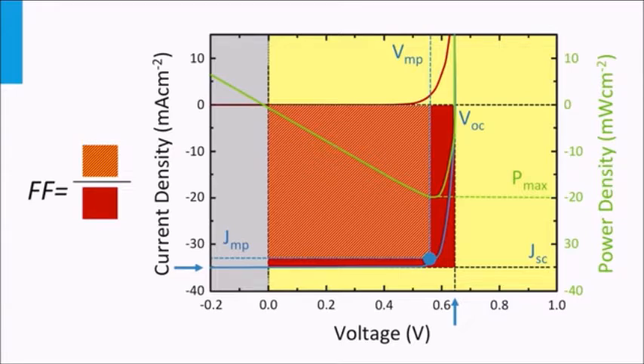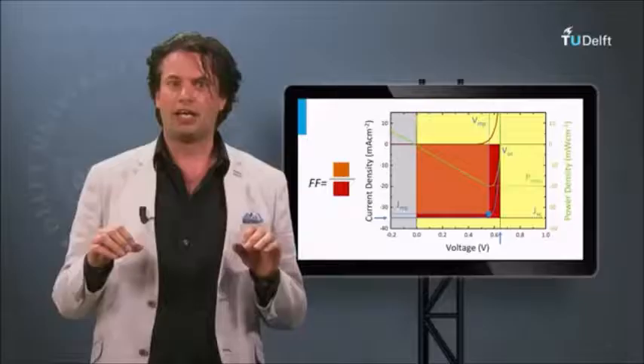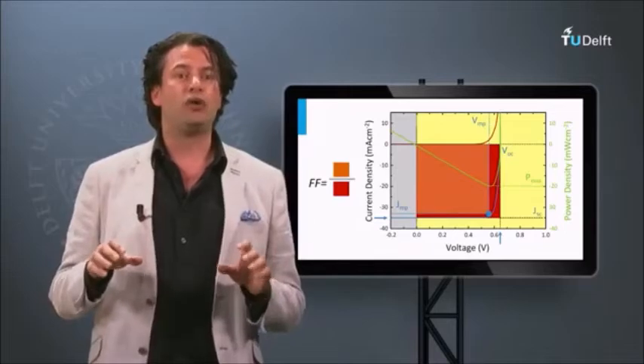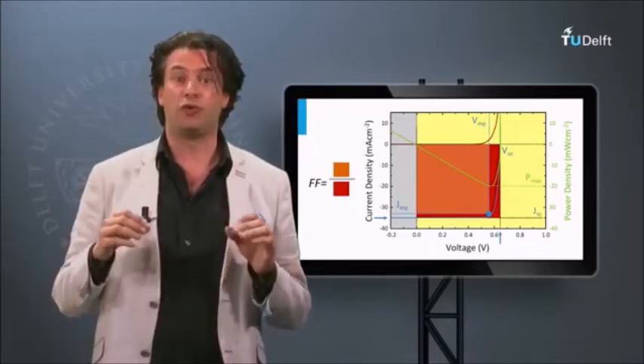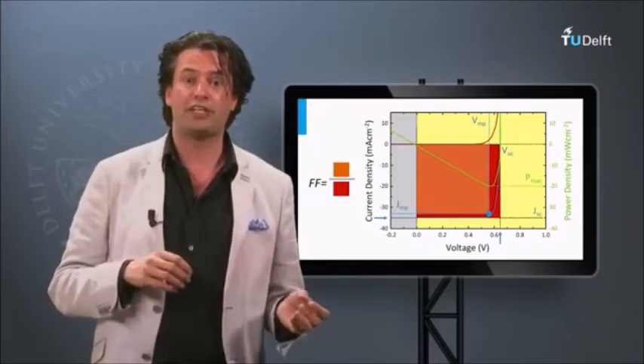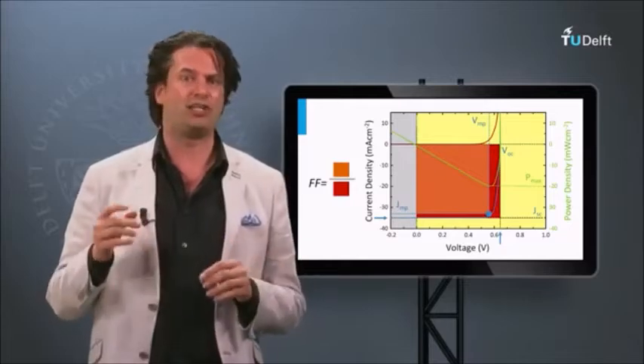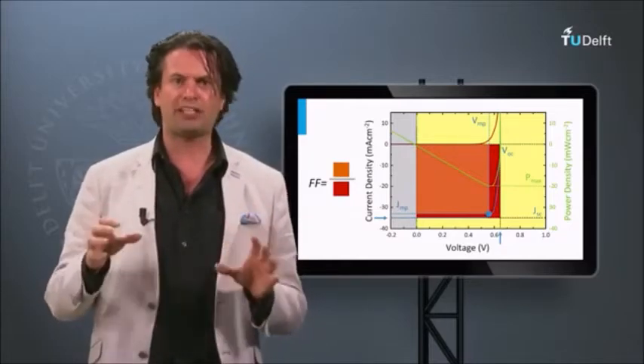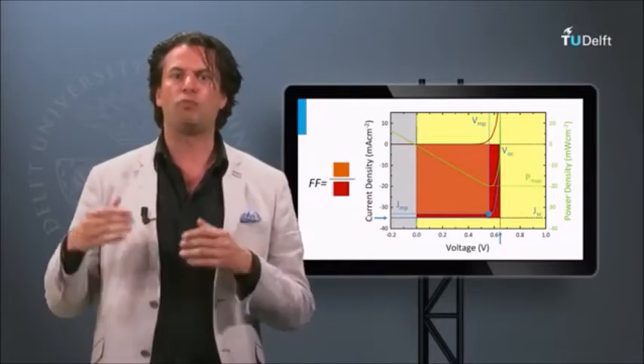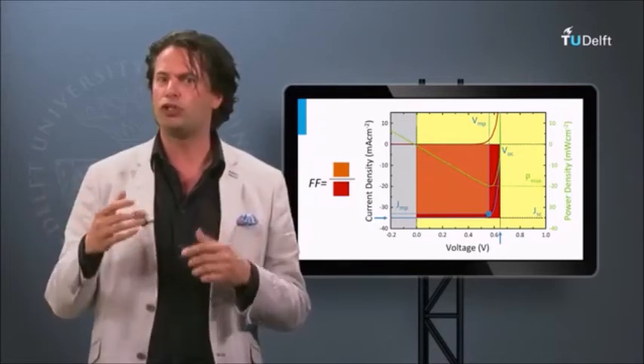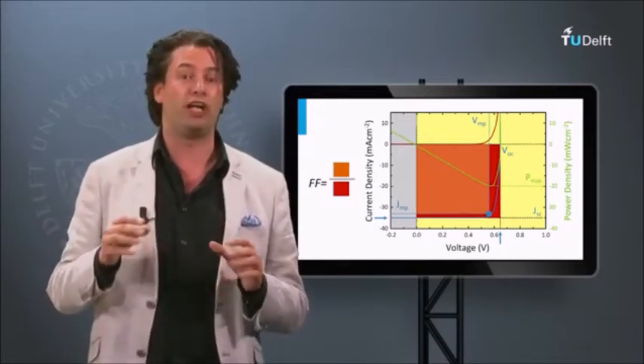It implies that it is impossible for a solar cell to have a fill factor equal to 1. In that case, the JV curve should have the shape of a rectangle. In the homework of this week, we have an exercise in which you have to derive a relation between the fill factor and the open circuit voltage of an ideal solar cell. This expression will show that the larger the open circuit voltage, the closer the fill factor will be to the value of 1.